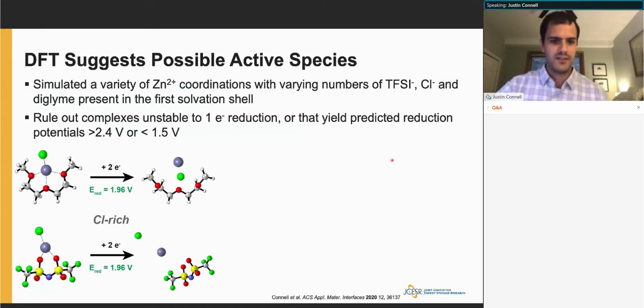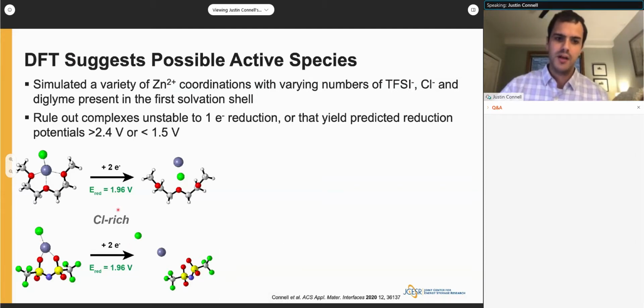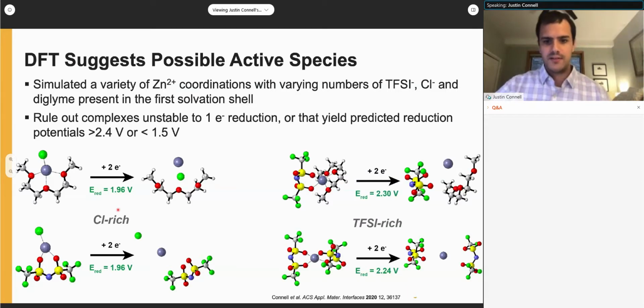One set of complexes which are chloride-rich, where we either have zinc solvated by a diglyme and a single chloride anion, or zinc solvated by a chloride anion and a TFSI anion. They both give relatively similar reduction potentials. What we also see is several stable TFSI-rich coordinations, with one TFSI and one diglyme, or with two TFSI anions, both again giving fairly similar reduction potentials.